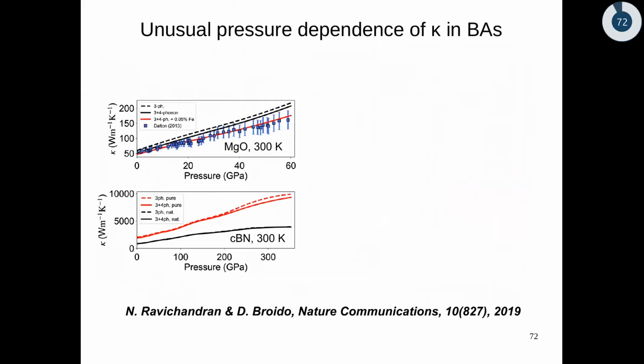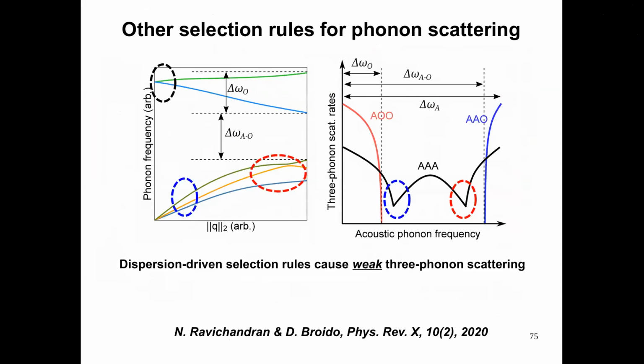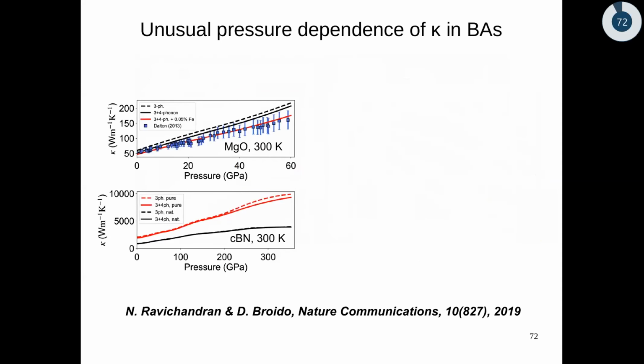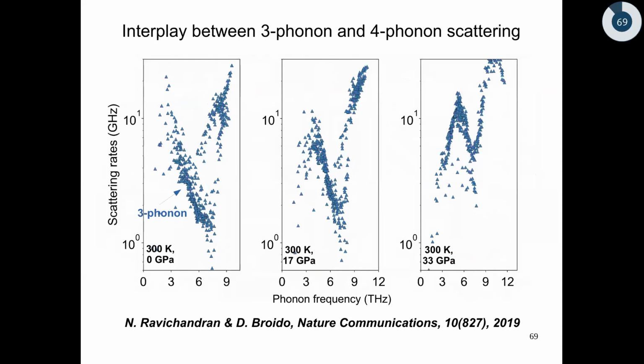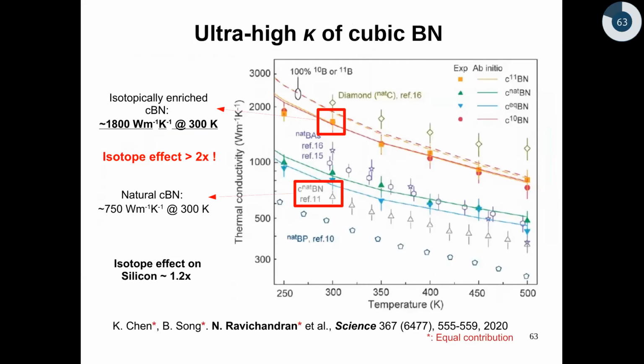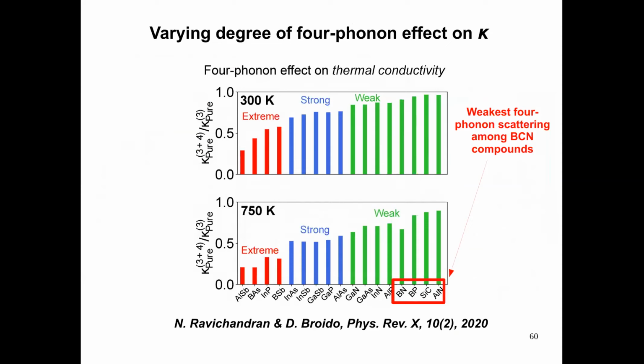Yeah, so that was the motivation for this work. We wanted to get some insight just by looking at the phonon dispersions, whether we can predict a material will have a strong 4-phonon effect or not. So this paper contains these selection rules related to the joint density of states, and you can identify, based on just the dispersion, which of these scattering channels will have anomalously weak joint density of states. What we find is that in the case of 4-phonon scattering, the joint density of states is not sensitive to specific features in the phonon dispersion. And additionally, we find that materials containing boron, carbon, and nitrogen atoms typically have weak anharmonicity. So with these 3 ground rules, we will be able to predict this plot, for example.